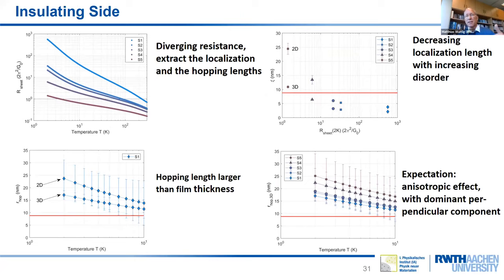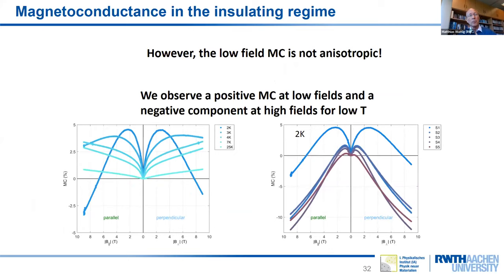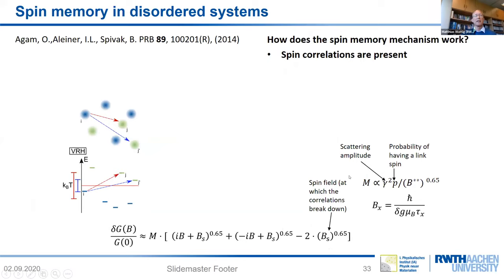On the insulating side, there's a divergent resistance. We can extract the localization and the hopping lengths. And the localization length is decreasing with increasing disorder. The hopping length is larger than the film thickness, so we have to describe this in the 2D limit. And we can also see how this depends upon temperature. Now, the important point is that we have a positive magnetoconductance, and this is symmetric. It is no longer anisotropic, it is isotropic. So an isotropic positive magnetoconductance, whereas before, in the metallic state, we had a negative magnetoconductance, which was anisotropic. And this is no longer the case here. So clearly this is isotropic behavior. This must be a very different mechanism. And it could be shown recently that this is a very special spin memory effect.